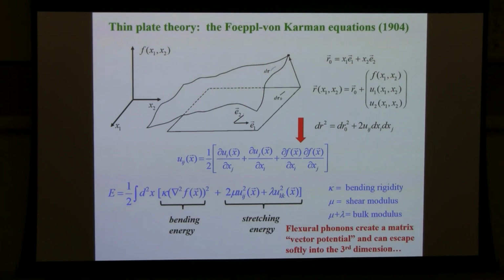And if you go to high enough temperatures, it's believed, although never demonstrated experimentally, that graphene will go through a crumpling transition where you would have to take into account the twisting and turning of the topology. But F can also be multivalent then. Well, if it's really crumpled and you insist on using this Monge representation, it will surely be multiple valued. But you can also look at an internal coordinate system. After all, this is a piece of graph paper. And if I just look at the blue lines on this graph paper, that's a coordinate system where everything is well defined. So it's a great question. I can elide over it for this talk, but in general, you would have to look at it, especially above the crumpling transition. Other questions?